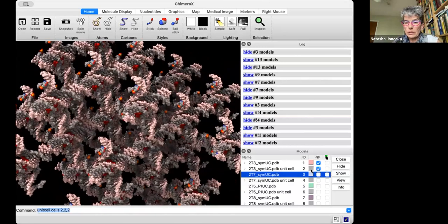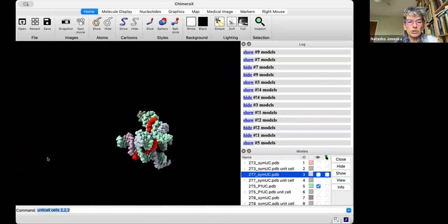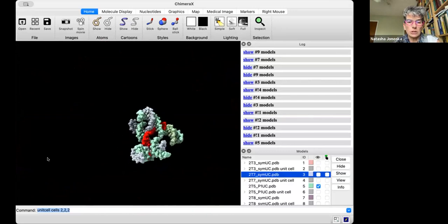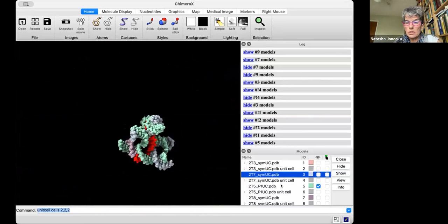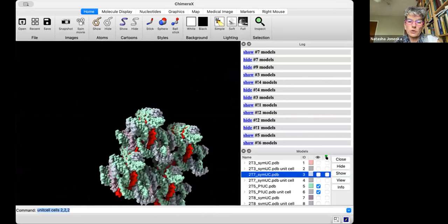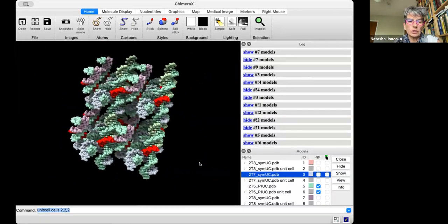And here's 5 nucleotides between junction and junction. There's no triangle. Actually, the 5 doesn't form a triangle. It just doesn't like to be a triangle. It does form a crystallographic structure, but it doesn't form a triangle.